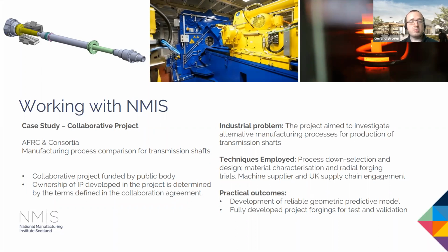And the practical outcomes for this particular project: we developed a reliable geometric model for radial forging, which we can now use for most of our radial forging research through the technologies that Javad has previously shown you. And we also fully developed project forgings, which were able to go on to be tested and validated in their final use.